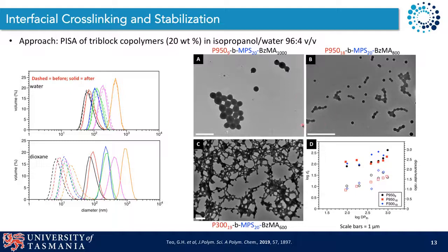What you'll notice is that we didn't actually form, even for very asymmetric block copolymers, anything other than spherical nanoparticles, again attributed to the fact that this long stabilizer block with the MPS group at the surface is essentially restricting the rearrangement to form higher order structures.